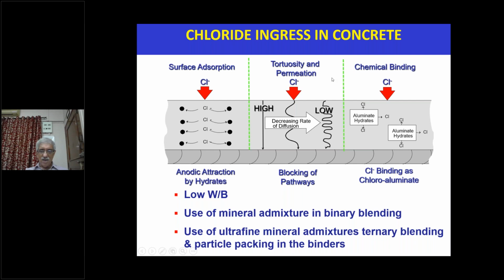Chemical binding, if we are using aluminate, slag, etc., then the chloride will hang on to the various particles of slag and are prevented from reaching the steel. And all this together shows that low water to binder ratio is very important. Use of mineral admixtures in binary blending and use of ultrafine mineral admixtures, ternary blending, and particle packing play an important part in preventing chlorides from reaching the steel, and therefore durability loss is arrested.